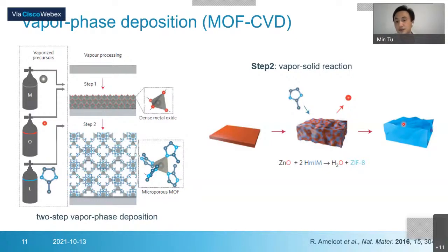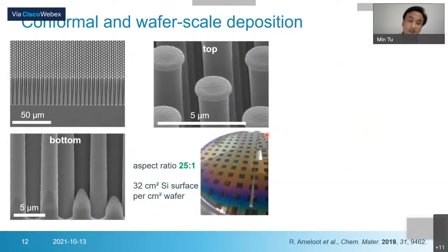Then it has a very homogeneous and porous structure. You can see from the scheme that zinc oxide typically has higher density. When converted to the porous structure, the density gets lower, and you can see the thickness expansion. So we can get different thicknesses of MOF film by tuning the thickness of the precursor layer. The key advantage of this method is conformal and wafer scale deposition.